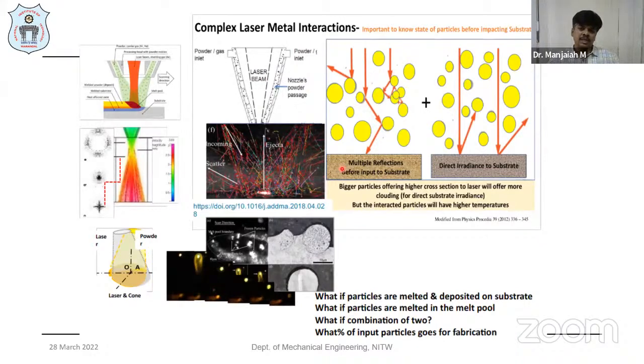Sometimes it may reflect the powders back before they are input into the substrate. And it may be ejected from the melt pool. It may be scattered because of the laser beam. It may be reflected, or scattered from the incoming powders. It may be melt ball formation or bar formation. And some of the fewer particles are ejected from the melt pool. These kinds of difficult, complex constraints are there in the electron beam or laser beam interacting with the powders.